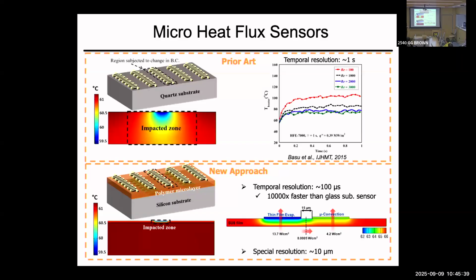And then we applied a 10 times higher heat transfer coefficient, assuming that the film comes over the surface at this location. And then all of a sudden you see a drop in surface temperature and heat starts to come from everywhere. So now, even if that process is sustained, it takes seconds for these processes to essentially continue. You don't even know the heat flux is coming from everywhere. So you can't really use this tool to study boiling, because boiling happens in milliseconds, as you will see.